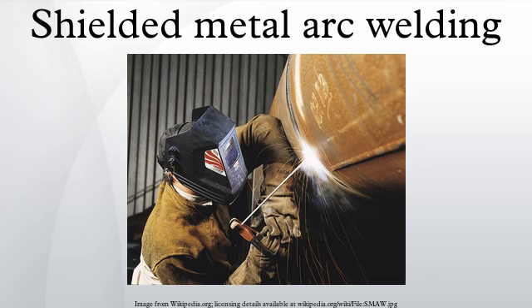Quality. The most common quality problems associated with SMAW include weld spatter, porosity, poor fusion, shallow penetration, and cracking. Weld spatter, while not affecting the integrity of the weld, damages its appearance and increases cleaning costs. It can be caused by excessively high current, a long arc, or arc blow, a condition associated with direct current characterized by the electric arc being deflected away from the weld pool by magnetic forces.